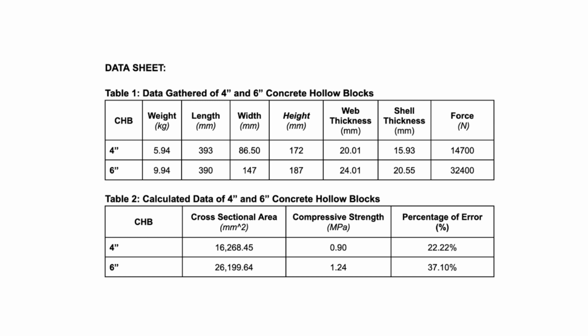Additionally, after testing the 6 inches CHB, it was found out that although its web thickness of 24.01 millimeters met the ASTM C90-23 standard of 19 millimeters, its shell thickness of 20.55 millimeters fell short of the minimum requirement of 25 millimeters. For ASTM C129-23, both the shell and web thickness of the 6 inches CHB meet the minimum standard of 13 millimeters.